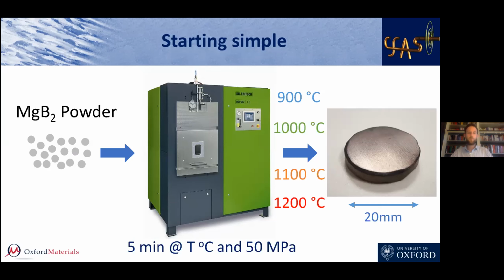But one of the most important parameters, the sintering temperature, which is well known by ceramics engineers to have the biggest effect, it wasn't too clear what it was doing to MgB2. So we started simple and had some MgB2 powder pre-synthesized and then sintered it at different temperatures from 900 to 1200 degrees C. And we obtained those little pellets, slightly bigger than a 1 pound coin, 20 millimeters in diameter. And then with those bulks, we could do our characterization.